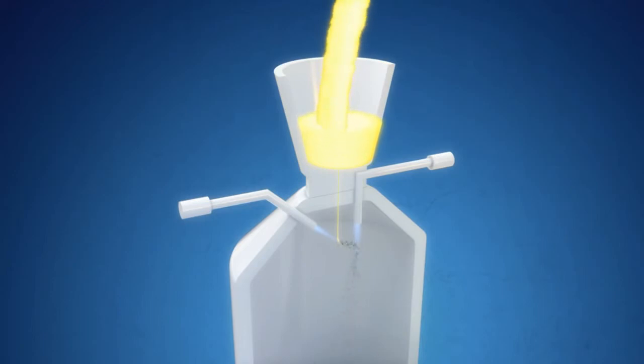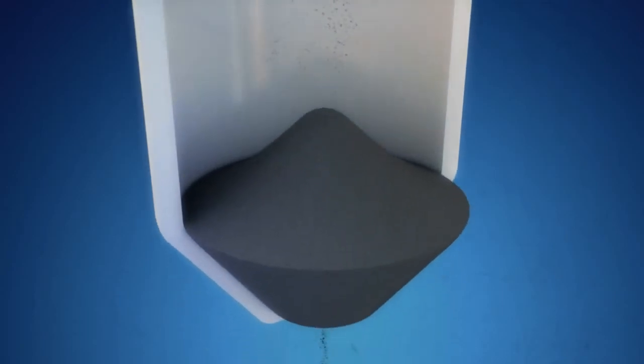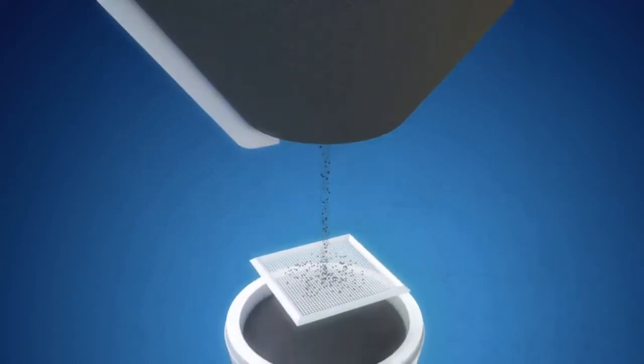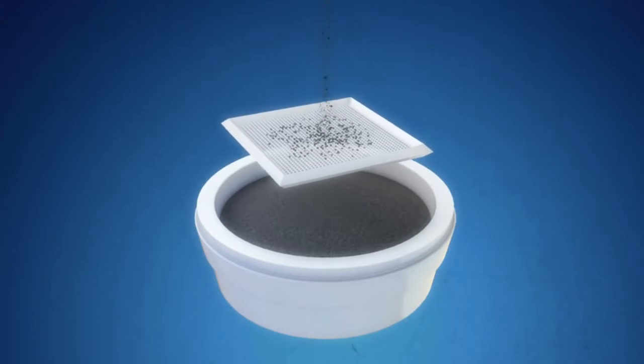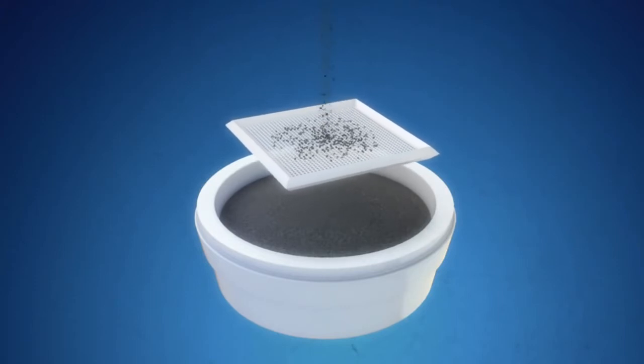Rapid solidification of the melt produces a metal powder with a fine-grained microstructure. The metal powder is collected at the bottom of the atomizing tower. To ensure a consistent and homogeneous powder quality, larger particles are removed.